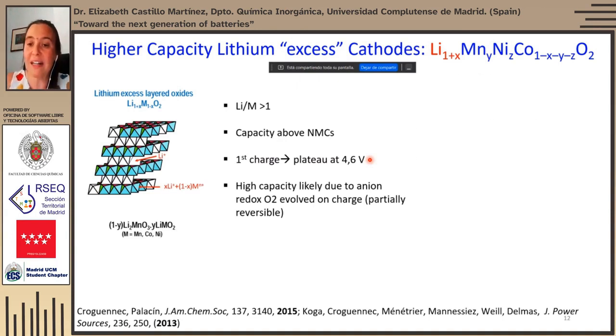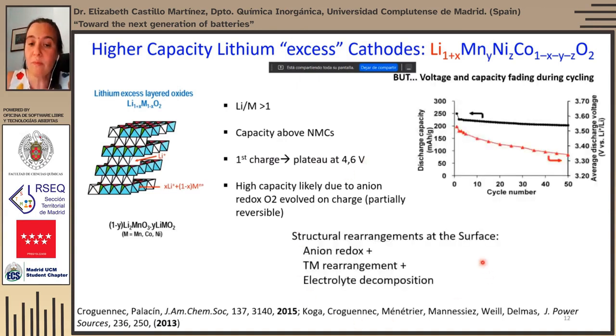In the surface of the particle, there is some oxygen loss, I mean, anion redox. And this leads to transition metal rearrangement. And because there is a transition metal rearrangement, the voltage of reaction changes. So what is observed in these materials is that the capacity, the discharge capacity, as well as the average discharge voltage, goes down as we are cycling. So despite these materials having very high capacity, they still have some issues that keep them far from commercialization.